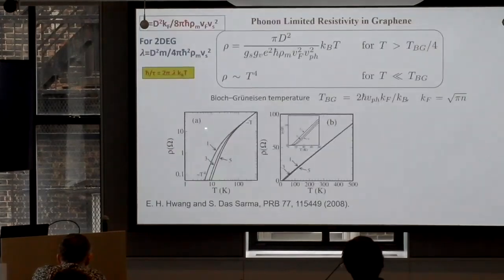This is what we did. We just did a first principles calculation of resistivity and Tc in monolayer graphene, because of electron-phonon deformation potential coupling. And you get the standard answer that you expect, at high temperature.